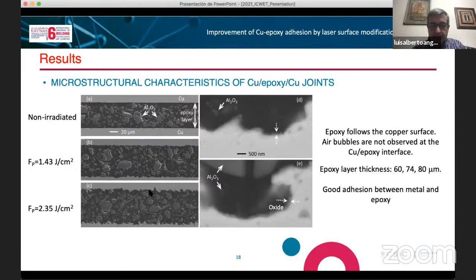You see how the roughness increases when we increase the fluence, but even with this roughness, you see that the interaction of the epoxy with the copper is very good, and the epoxy follows all the topography on the copper. Also here you can see the oxide that the laser treatment has generated on top of the surface of the copper. One difference that we have observed is that even though in all the cases we apply the same pressure, the thickness increases with the increase of the roughness of the copper layer.